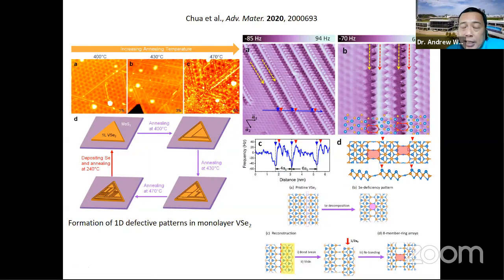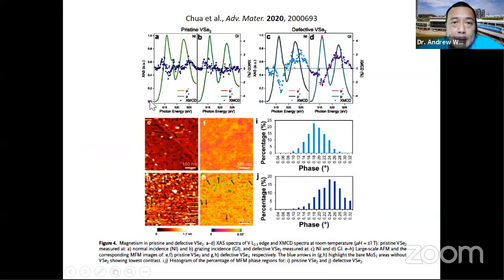So that's the line defects, and you can increase the line defects on this vanadium diselenide monolayer simply by annealing. And these are the magnetic measurements. The XMCD on top shows that there's no magnetic signal when it's pristine, but the defective vanadium diselenide shows a weak but discernible magnetic signal, a dichroism signal, right? And at the bottom, the MFM images: on top is the pristine, and the bottom is the one with defects, and I think this on the right is the phase spectra. You can see some difference in images, but if we look at the statistics of the percentages at different phases, you can see a shift.